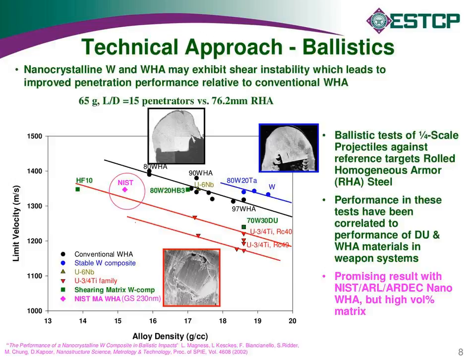The next slide shows what we were going to do. We have a large database for both conventional tungsten heavy alloys as well as DU alloys for a standard set of rods. These are all 65-gram mass rods. This particular plot is showing the data for L/D, length to diameter ratio, of 15. So the rods are 15 times the diameter in length. And on this plot, I'm plotting limit velocity, which is the velocity required to perforate this given target. In this case, it's a 3-inch plate of rolled homogeneous armor as a function of alloy density. So if you look at the line with the black data points,